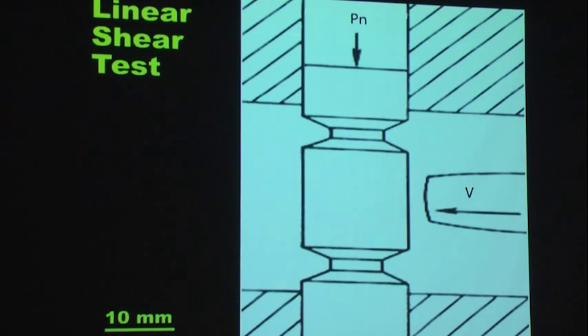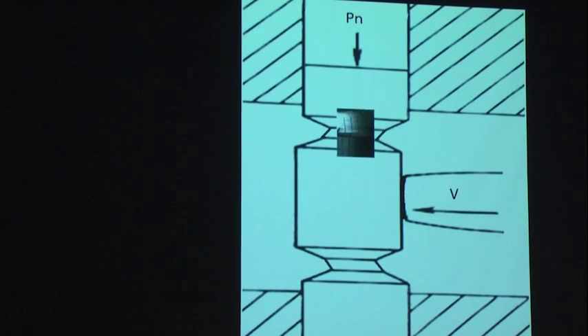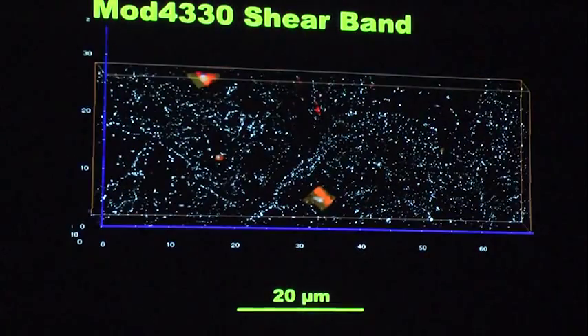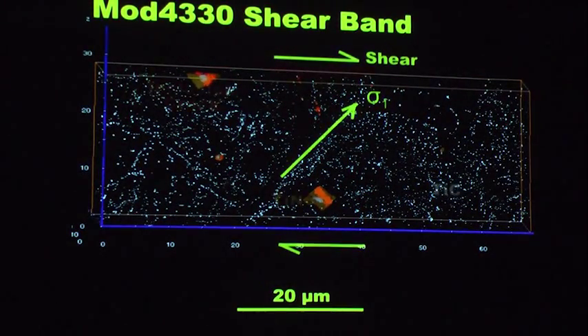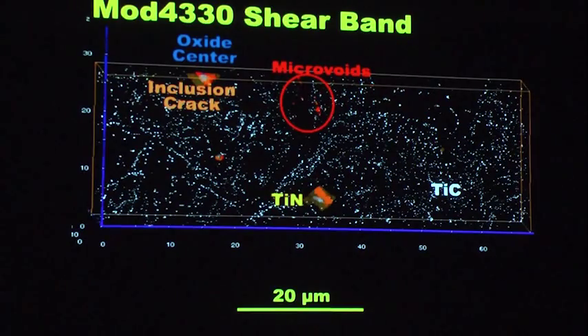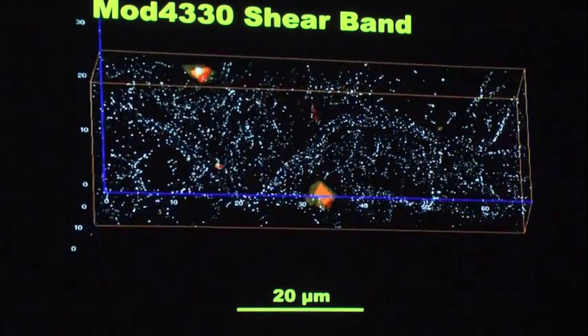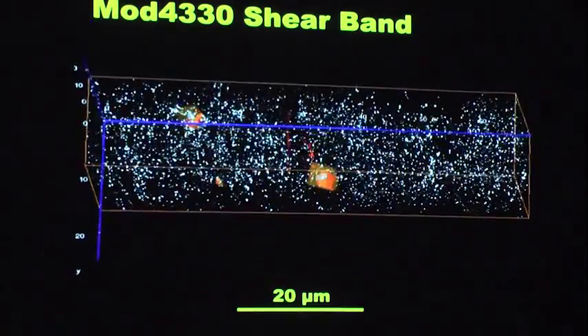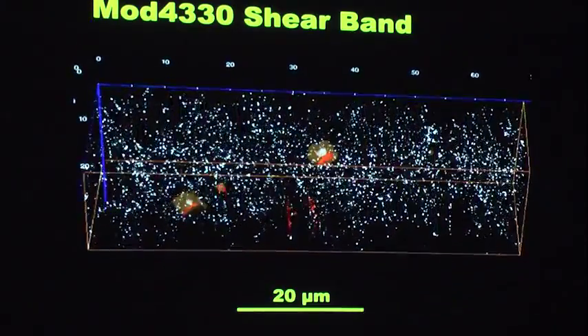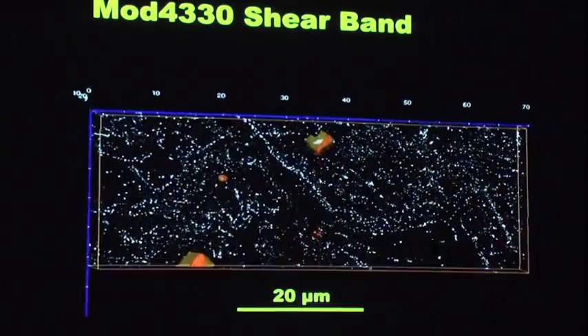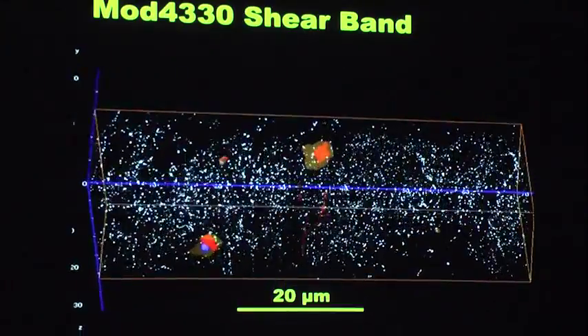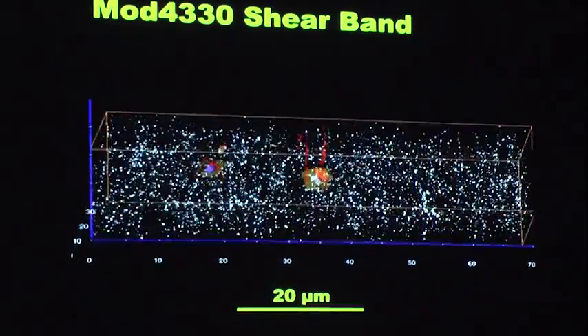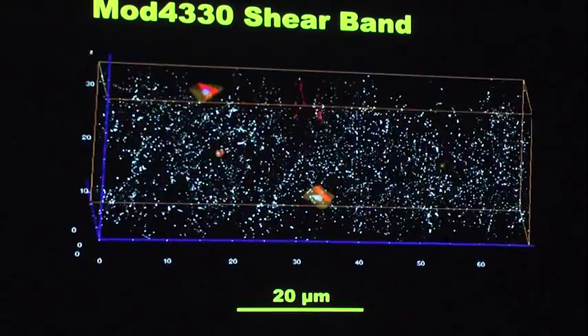Now, the way we validate that is we're taking the material under a linear shear test to the onset of the formation of a shear band, and then by FIB-SEM reconstruction, cutting out that shear band. And here, shown in red, we're able to capture one of the first clusters of those microvoids, very similar to that simulation. You can see as we rotate it around, the primary inclusions are also cracked by the principal stresses. And you can also see the anisotropy of this dispersion and how things line up when we look down the forging direction. Now, the context of this we're interested in is 45 degrees away in the context of the process zone of a mode 1 crack tip.